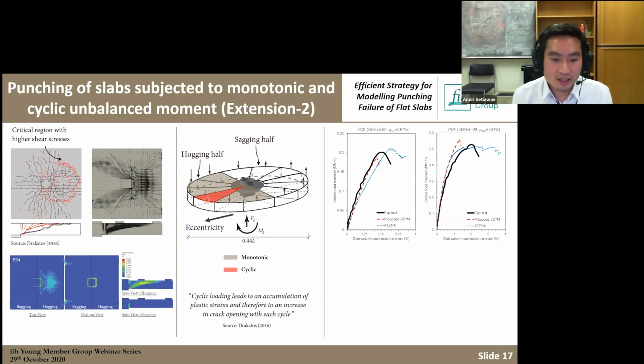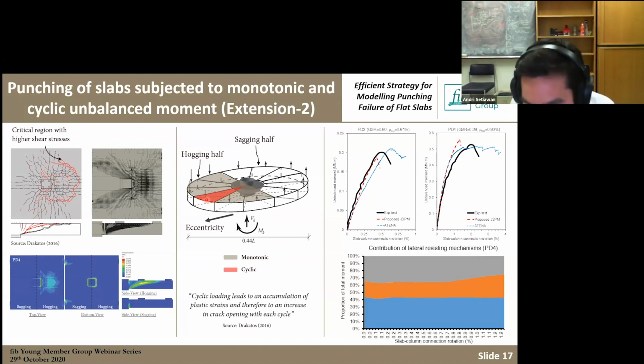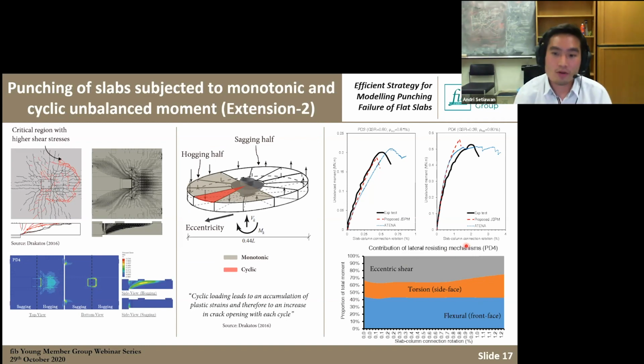And another interesting thing about the joint model is that instead of only just predicting the load rotation, we can also quantify the contribution of each transfer mechanism. For example, if you have slabs loaded in an unbalanced situation, you can carry the moment by eccentric shear, by torsion, and also by flexure. So by having joint elements, we can quantify that, which can be seen here. So we have the contribution of the eccentric shear, the contribution of the torsion side face, and the flexural front face. That's also one of the benefits of having this model.